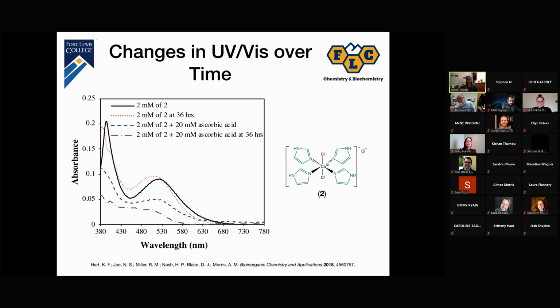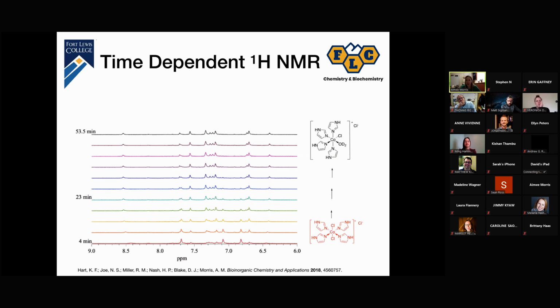So because we noticed these changes by UV-vis, even in the parent cobalt(III) complex, we wanted to investigate the kinetics of the ligand substitution a little bit further. And so I had my students run a whole series of NMR reactions. So we took the parent cobalt(III) complex, we dissolved it in D2O, and we took the NMR. And as quickly as we could dissolve it in D2O and get it into the NMR, which took 4 minutes to get everything set up and actually run the experiment, we already saw the appearance of some peaks that we don't normally see.